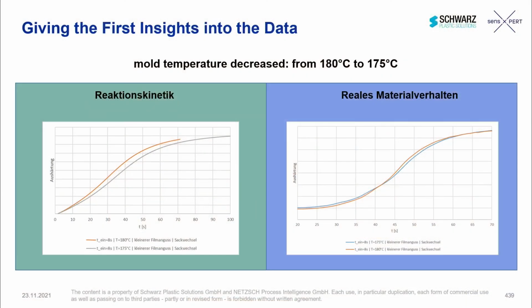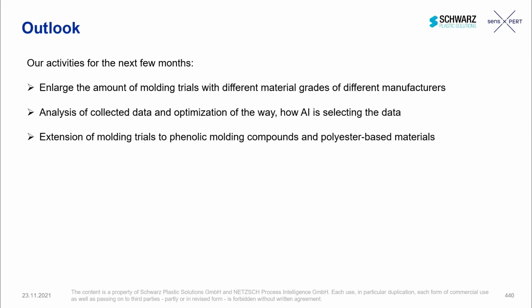Here, a change of just 5 degrees C in reaction kinetics should make a big change, but we can see in the real material behavior, it doesn't. So we have a slight change, but not that dramatic like we've expected based on pure reaction kinetic simulations with the basement of laboratory data.